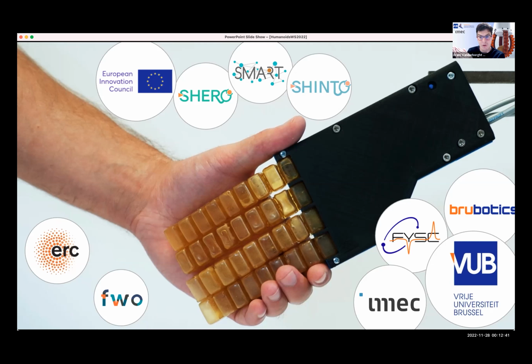And so typically network polymers, the polymer chains have crosslinks, and that gives very interesting properties to the material, but it also means that you cannot go to a flow behavior anymore, which is needed for 3D printing. That's typically the reason why with those network polymers you cannot do additive manufacturing. And that's also the reason why you cannot recycle them, because you can heat them up, but after a while they burn and do not go to a flow behavior.